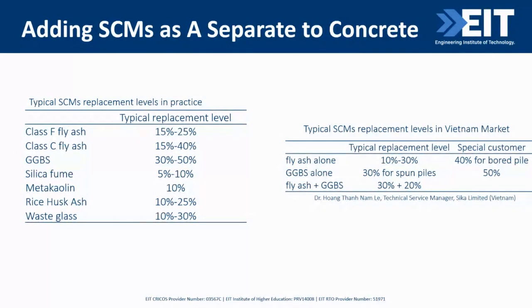On the right-hand side, I also gathered some data from a colleague of mine who's working in Sika Limited, Vietnam. According to the information, the trend of using supplementary cementitious materials in Vietnam actually began about 2 years ago, and the most typical supplementary cementitious materials in use are fly ash and GGBS. When fly ash is used alone, the typical replacement level is 10 to 30%. A few customers use 40% for bored pile, and some special customers use 50%, but only used in ready mixed concrete.